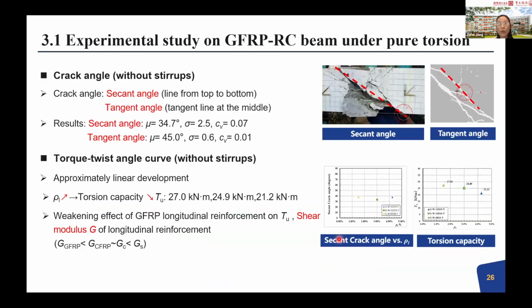Most important is the spiral crack angle. We found that right now we do not have a specific or constant regulation for the crack angle. How to calculate it, using the tangent angle at the center of the beam or using the secant, there is no consistent conclusion. So we calculated these two kinds of angle separately. We found that the tangent angle at the beam center is very close to the theoretical calculation based on elasticity mechanics.